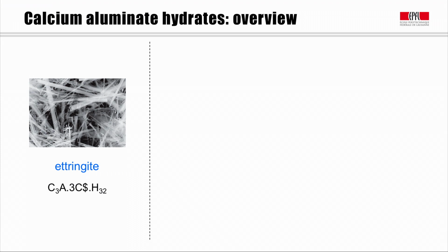These are very similar elements from a chemical point of view. And because of that, as well as the term ettringite, which means the form with aluminium, we also have the term AFt. So A and F means the possibility of having either alumina or iron oxide, and t is the other anions, that's to say in this case the calcium sulfate. And here we have 3 calcium sulfates, so 3 gives us the word tri.